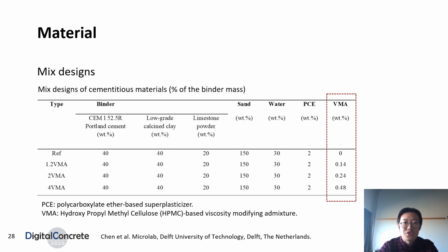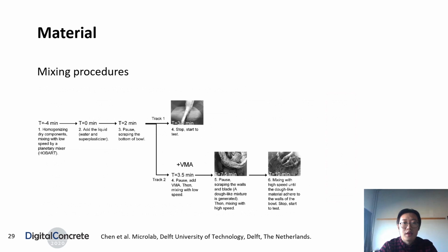The mix design of the studied mixtures is illustrated in the table. We kept everything identical except the dosage of VMA, from 0 to 0.48% of the binder mass. The REF mixture is prepared following track 1. The mixtures containing VMA are prepared according to track 2.